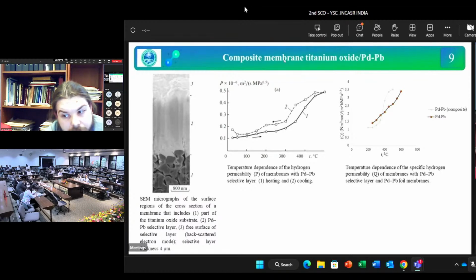The values of the hydrogen permeability of the membranes differing in the configuration are comparable. This indicates the fact that the hydrogen flow is inversely related to the membrane thickness, and the porous substrate does not affect the permeability of membranes.